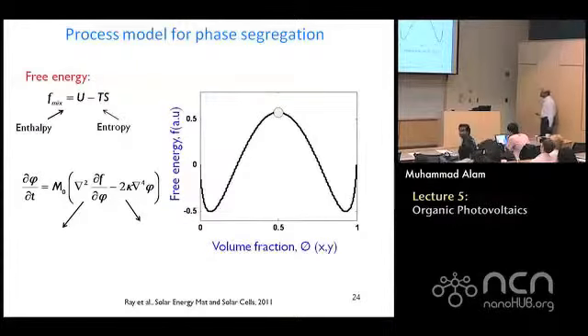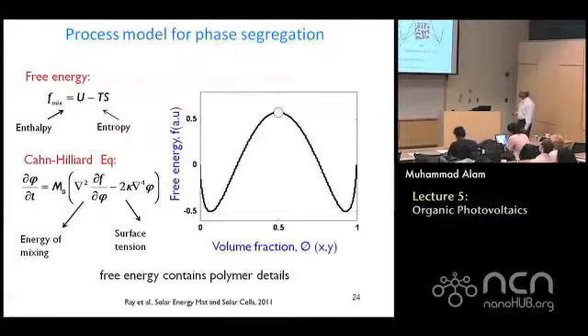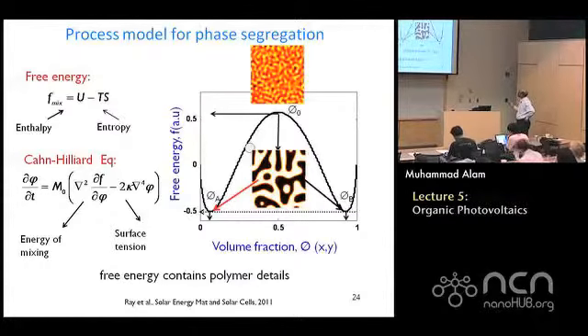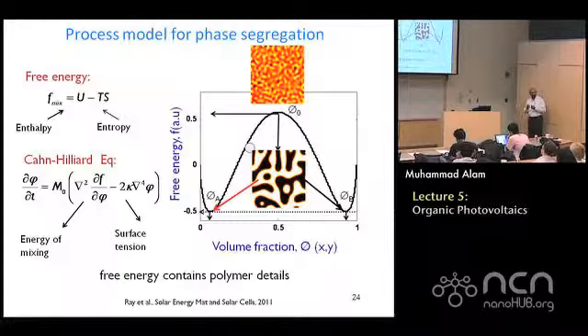That's fine. And I will very quickly tell you a little bit, because that's not the essence of the story, that if you start with a completely homogenized structure and then increase the temperature, there is a stable point here, and a stable point here, so that in the black region there is a little bit of white mixed up, and also in the white region there is a little bit of black mixed up. But on the whole these junctions are reasonably short, and so when you put your exciton in here, they will be separated. So it's not a pure phase. It is a little bit of a mixture of the other, but it's like 90% white or 90% black. So we shouldn't complain, because the junction is maybe a little bit lower than the pure phases, but still it will dissociate things.